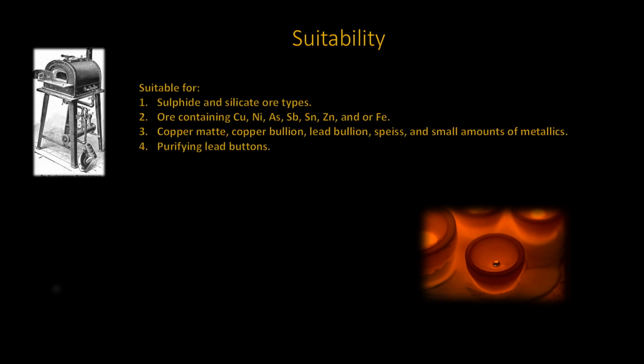As with any process, the ore concentrate has to be suitable for the method to be used. Ore that contains sulfides or silicates can be easily processed using scorification, especially those that contain contaminants such as antimony and arsenic, which are easily oxidized and readily slagged. After a crucible fusion and separation from the slag, you may find a copper matte. These can be easily processed and any trapped precious metals can be separated. Same with speiss. Copper and lead bullion can be assayed as well as small amounts of metallics, which results from the sampling of gold-bearing ore.